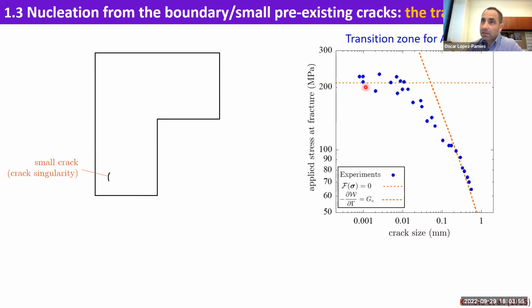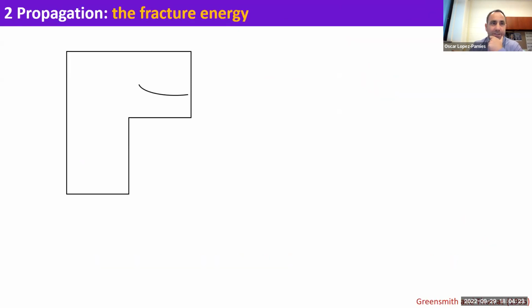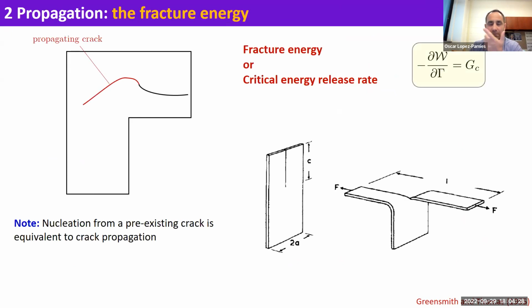What is happening here is very clear. You're making the crack smaller, and by making it smaller and smaller, you're making it comparable in size to the inherent defects that you have in your material. It is the inherent defects that control the strength of the material, and that's why you get a transition from Griffith fracture to a strength fracture. All right, so this is what we know from experiments. The propagation of fracture is also Griffith. This we know from experiments, so we know nucleation, we know propagation.